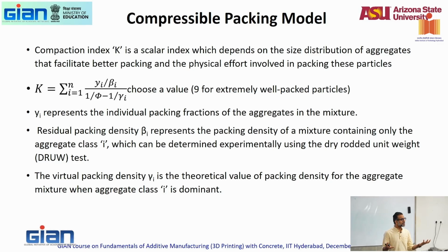Right now, you pack particles, it doesn't come free, it comes at the expense of energy. If you want to pack something more into a system, you have to give it energy, correct? You have to vibrate it, you have to rod it, you have to compact it, something, correct? Just by taking a bunch of particles and putting them in a volume, will it compact well? You have to vibrate it, you have to let it go into the right spaces to fill it, correct? Same thing with concrete also. You vibrate your concrete to get a better density. So you need to provide energy. So this K is an indication of both the distribution of particle sizes and the energy that you give. Through experiments, they have come up with lots of those numbers. You can use a value of 9 for extremely well-packed particles. 9 is a good number for extremely well-packed particles, irrespective of the size of the particles.